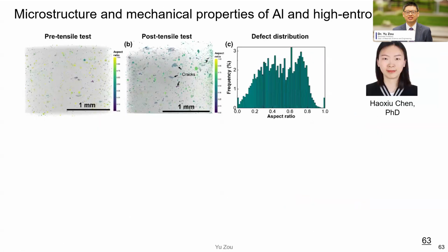Towards the mechanical performance, this project is mainly focused on the mechanical properties of aluminum alloy and high entropy alloy. This is a collaboration between my lab and the additive manufacturing team at Waterloo. So we did the tensile test of aluminum alloy, and then we characterized the process before the tensile test and after the tensile test to identify the failure mechanism.